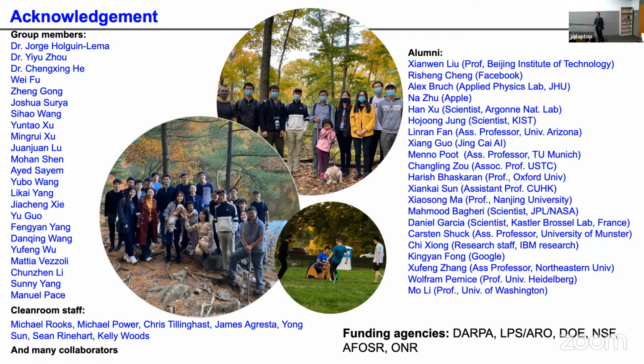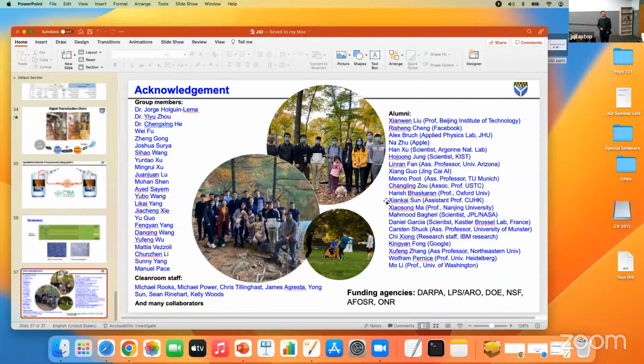You mentioned that you're able to use this r13 tensor coefficient, but you're using polycrystalline films. Does it require some order of the domains in the in-plane direction as well, or does it still give you an r13 even if it's polycrystalline?